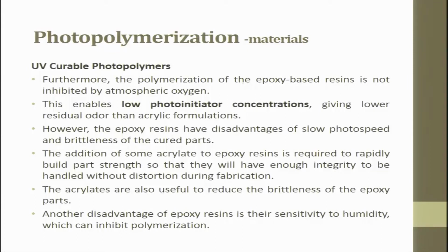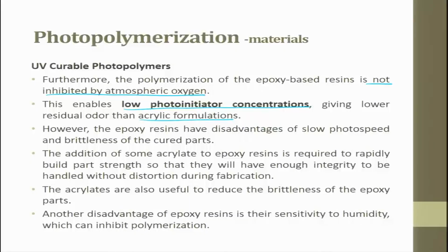Furthermore, the polymerization of the epoxy based resin is not inhibited by atmospheric oxygen. This enables low photoinitiator concentrations, giving lower residual odor than acrylic formulations. Okay. So it is not inhibited by atmospheric oxygen. Epoxy does not react with atmospheric oxygen. This enabled low photoinitiator concentrations, giving lower residual odor than acrylic formulations.